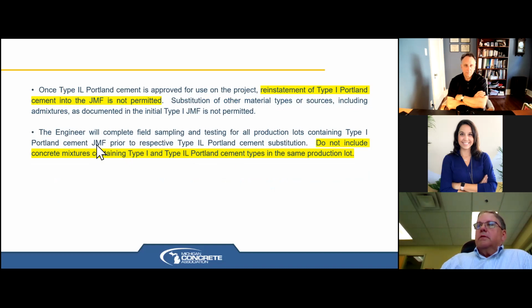The other requirement that we put in the spec was that the job mix formula and all the sublots have to be consistent. You don't want to mix type 1 with type 1L in a sublot. So on the project sites, the day they switched, they had to close out any existing sublots and start over with a new lot.